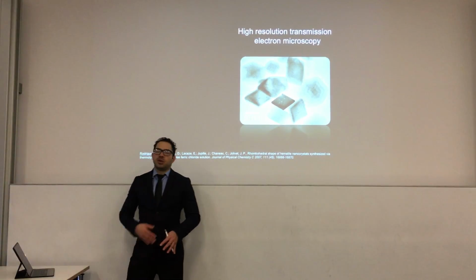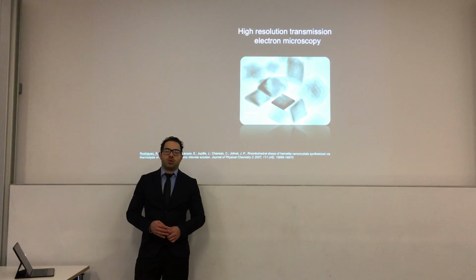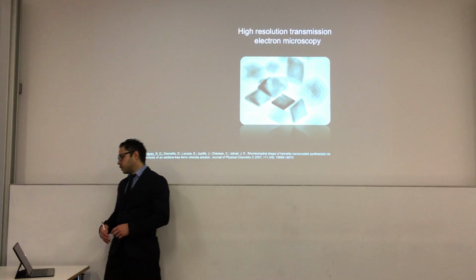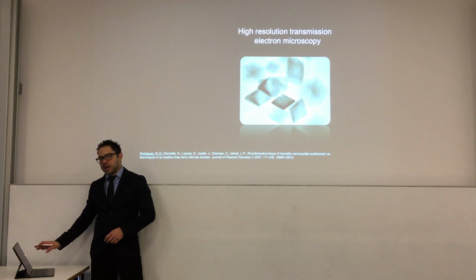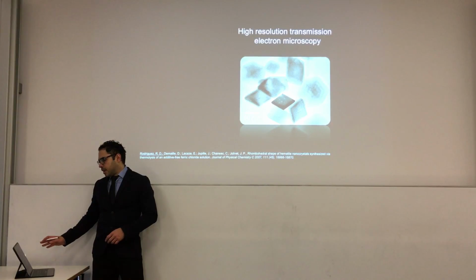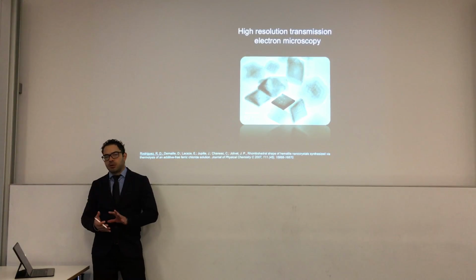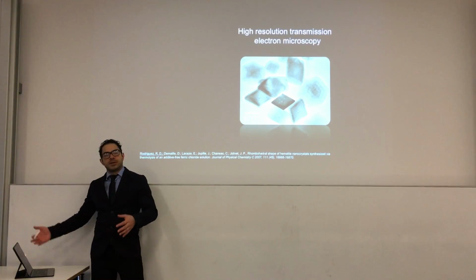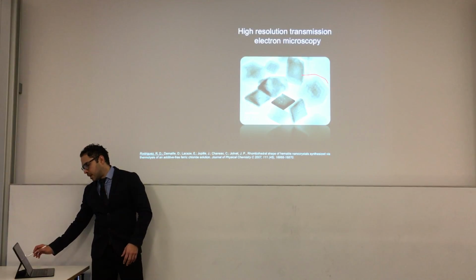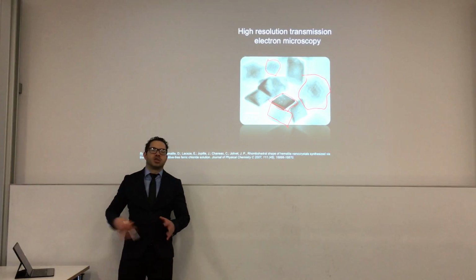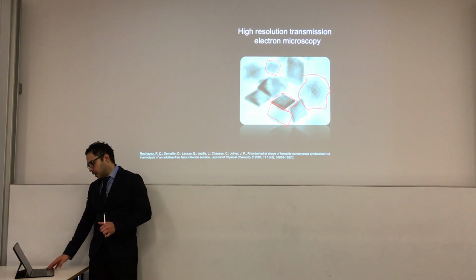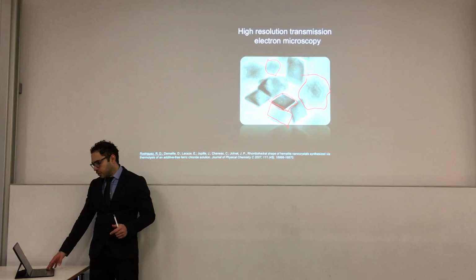Now, conventional methods that are used, for example, to investigate nanoparticles, such as electron microscopy, in this case is an interesting example since you have an iron oxide nanoparticle that shows different morphologies. For example, you see some hexagon plates there. You see also some rhomboidal particles, some rectangular particles, or a bit more cubic or spheroids. So you have a zoology of different shapes that you can see in the high resolution microscopy.